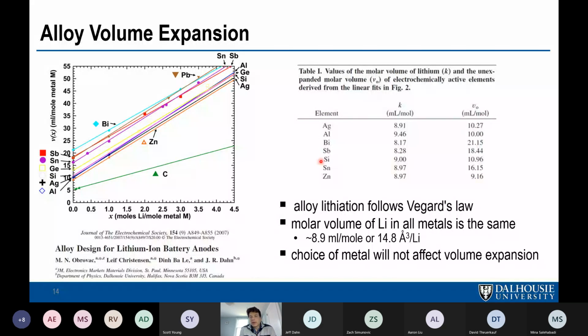An important aspect of getting these materials to work is the volume expansion. So early on, one important thing was, well, silicon is cheap, but expands a lot, and all these materials expand. Does one material maybe expand less than another? And maybe that would make it more attractive. And so at 3M, we plotted all the known intermetallic lithium phases, and this just represents some of them, as the number of lithium you can put in per host metal, and on the y-axis, the volume per host metal. And if you plot in this fashion, you get a linear trend, and the slope of this line represents the volume of an atom of lithium in the alloy. And you could see it's the same for any alloy that you pick.